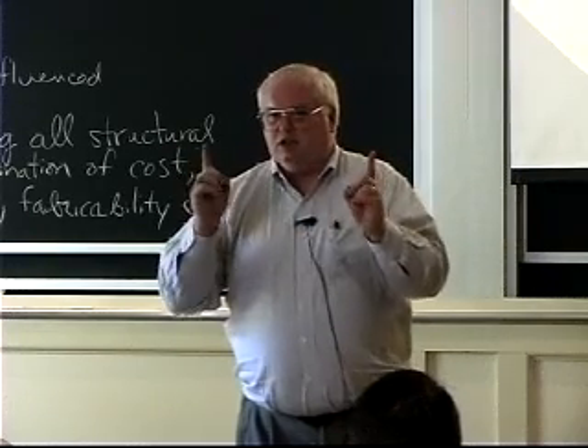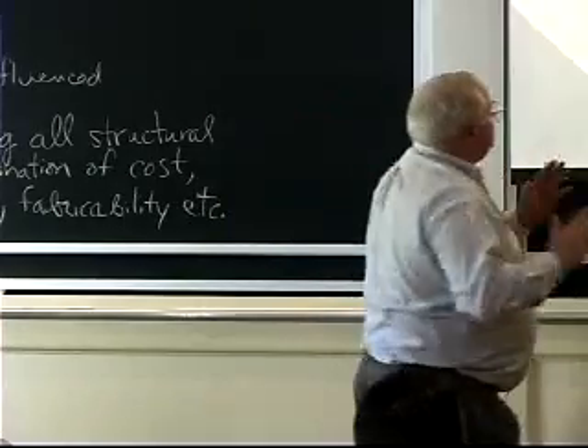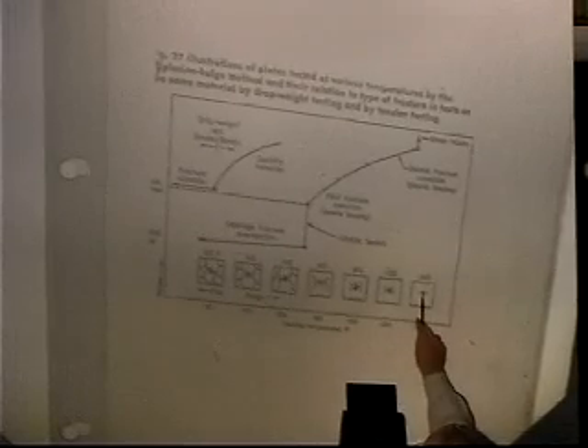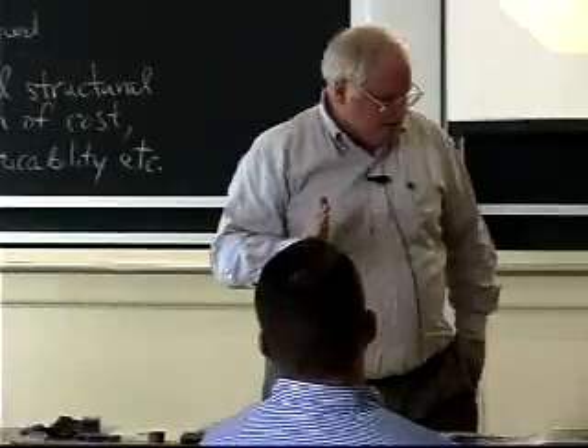They decide that's not a good steel. That's not a good welding process. And this is actually what they've got here: different testing temperatures, the results of an explosion bulge at 140 degrees Fahrenheit. You go down in temperature and steels become more brittle, and some of them just shatter like that. Okay, but you did that with aluminum, you look at it cross-eyed, it would shatter.